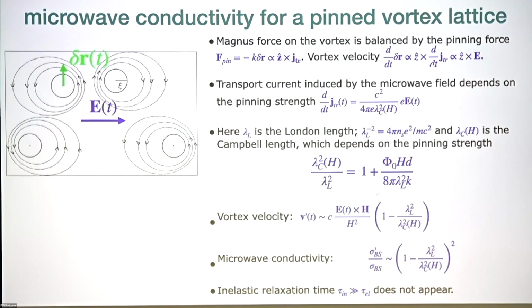And so to find this coefficient, you have to basically relate the time derivative of the transport current to the electric field. This can be expressed in terms of the effective macroscopic superfluid density of the sample. Traditionally, the superfluid density is expressed in terms of the London length. It's analogous to the relationship between the superfluid density and the London length. Now, the macroscopic density of the sample depends on pinning, and is characterized by the Campbell length instead of the London length. And the ratio of the Campbell length to the London length depends on the spring constant, K, of the pinning, and depends also on the magnetic field.